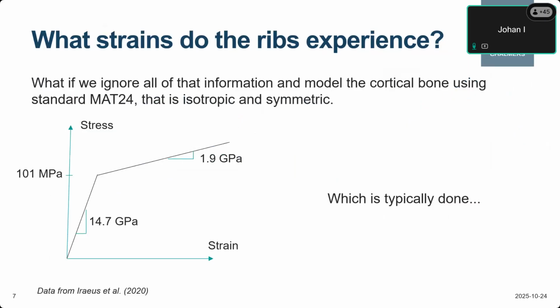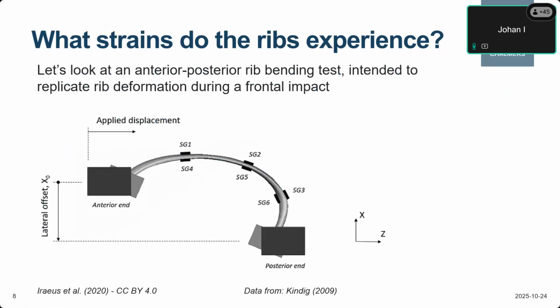So what if we ignore all this information and model the cortical bone using a standard MAT24 that is isotropic and symmetric, which is typically done? Here we have some data which is basically averaged over Kemper data from 2005 and 2007. If we then use that for a model of a rib, this is a setup replicating physical tests from Kindig's PhD thesis, 2009. This is bending of the ribs in pure anterior-posterior direction. So we hold this cup fixed and we move this box in the same direction, and we bend the rib.